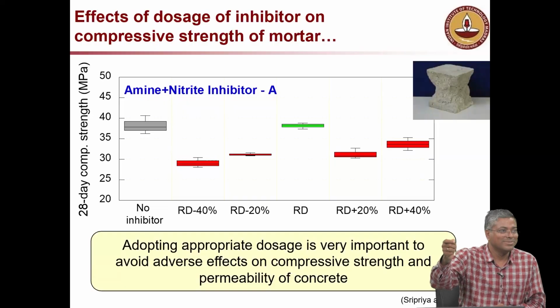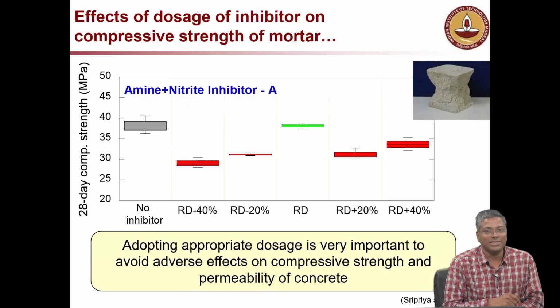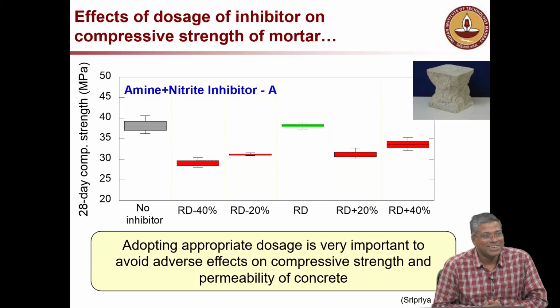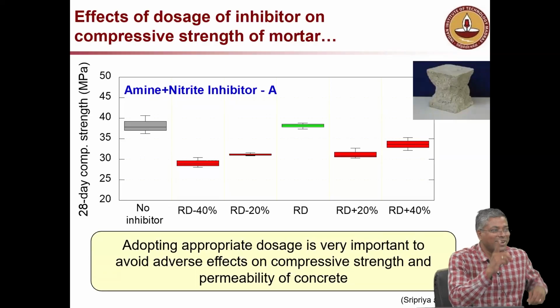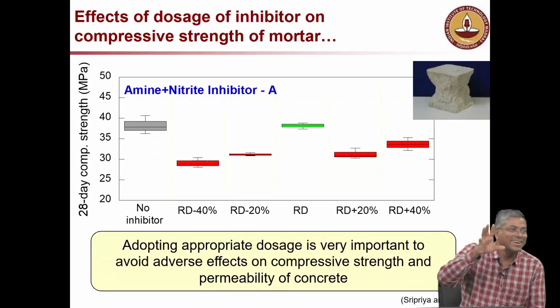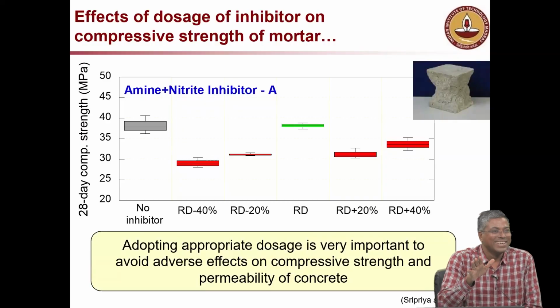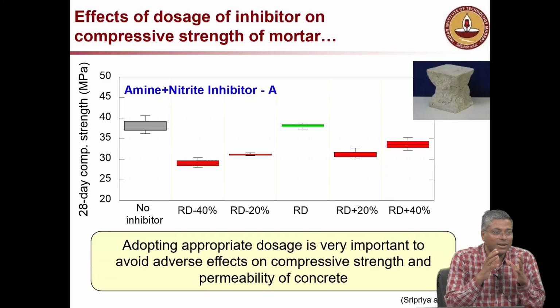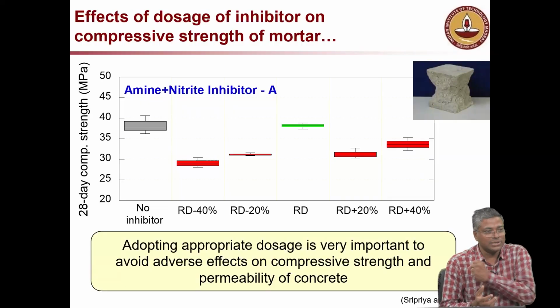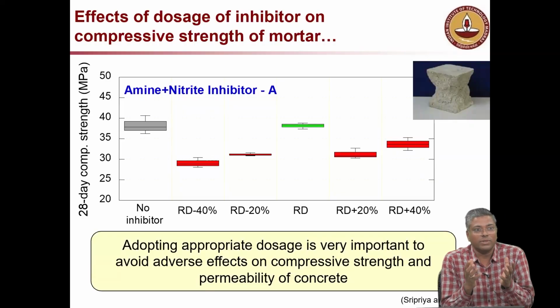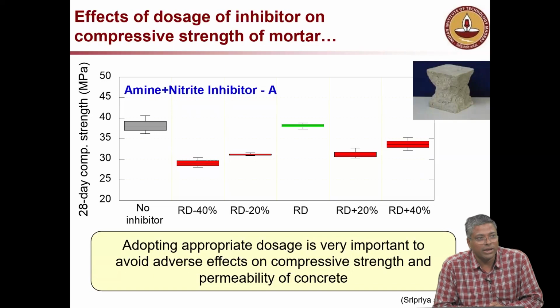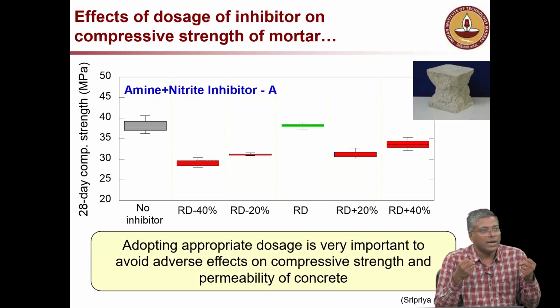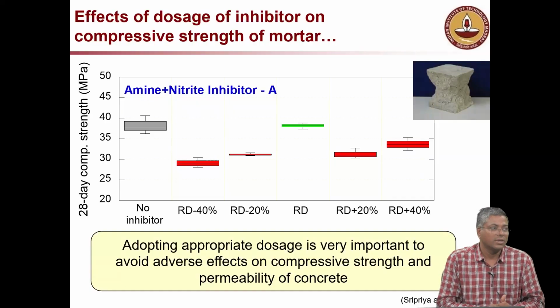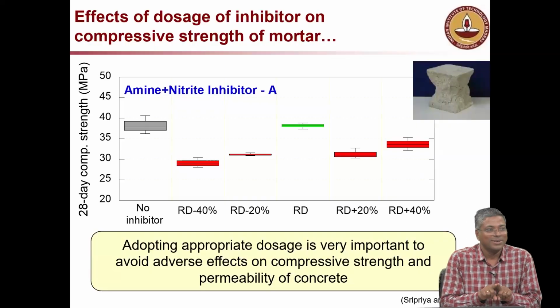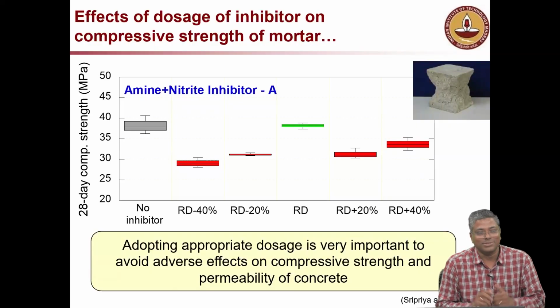Yesterday you might have seen, no? What was the problem yesterday in SCC? It was not SCC, right? What was the problem? Did you ask? Today you ask, okay? Why it was not SCC? Because today Umesh and the team are working on ensuring that it really flows. Yesterday they did not consider the dry aggregate, the water content. So the aggregates absorbed all the water and it was not available. So moisture content of the aggregate is very important, coarse and fine aggregates. Otherwise, the water will be absorbed by the aggregates and it will not be available for the cement. So that's what happened yesterday. Mix design was good, but moisture correction was somehow missed. Okay.